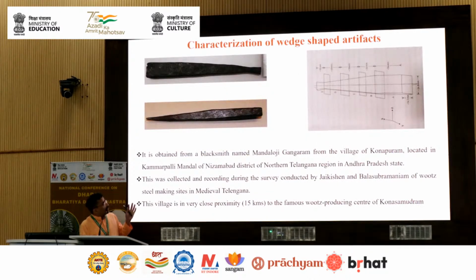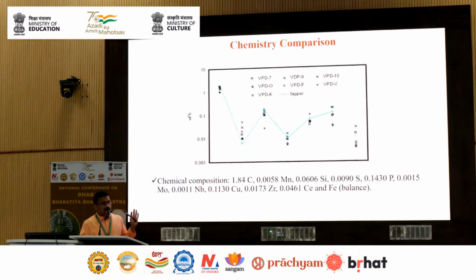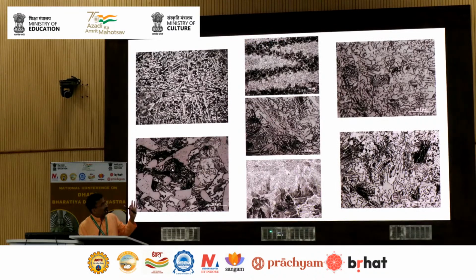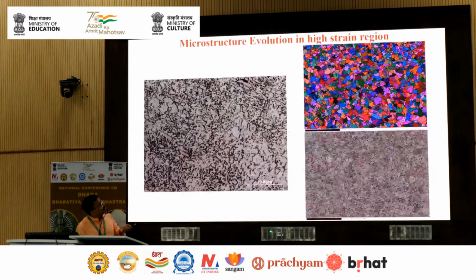Now this is the sample we have procured near Konasamudram, during the survey of South India. Jaikishen has helped us a lot, and it has been characterized, and we found that chemistry-wise this sample falls in between other Damascus swords. We also observed that cerium and niobium type alloying elements were present. These are the microstructure evaluations, from low strain region to medium strain region and to very high strain region, and we were able to see a random distribution of ferritic grains, and there was also carbide banding.